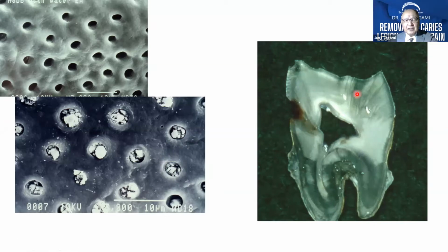This is another specimen, a thin sliced polished specimen. You can see the caries here, and at the bottom of this caries region, you can see the transparent dentin formation. This specimen was obtained from an elderly patient. That's because of aging, even in the intact dentin area, we could observe some kind of transparent dentin.